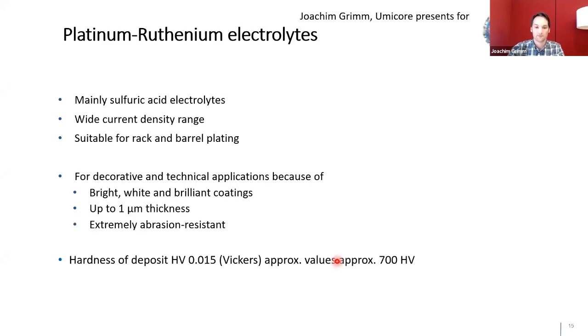Okay, now it works. So the third electrolyte system I explained to you was the platinum-ruthenium electrolytes, which, same as platinum, is a sulfuric acid based or phosphoric acid based solution. So it's strongly acidic, with the same wide current density range, and suitable for racks and barrels. You can go up to 1 micron with this white and shiny layer. Even though it's a little bit more grayish dark than the rhodium alloys, it's extremely abrasive resistant and perfect as an intermediate layer. And you can reach hardness up to 700 Vickers with that.